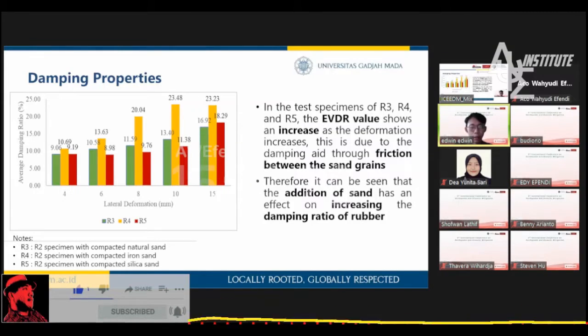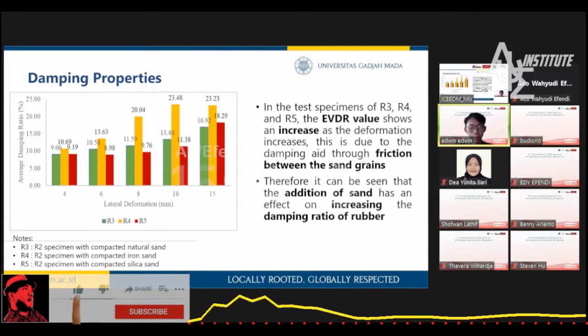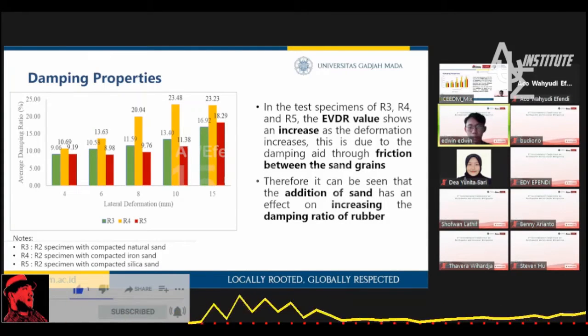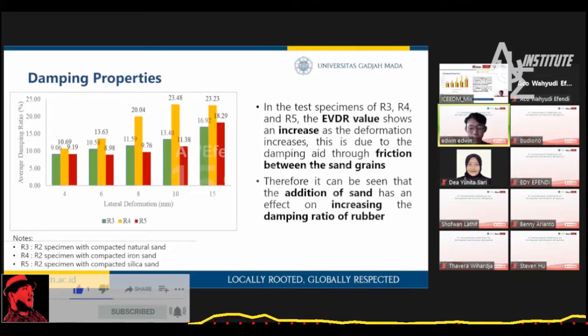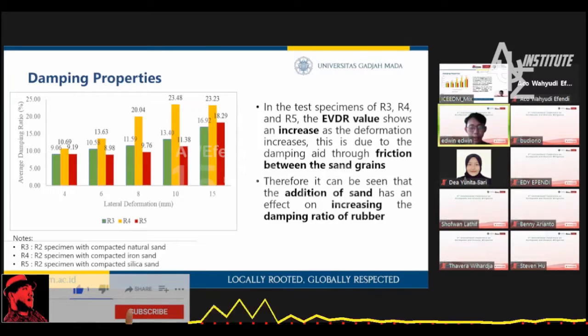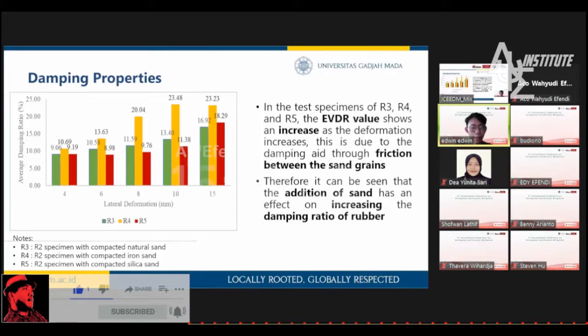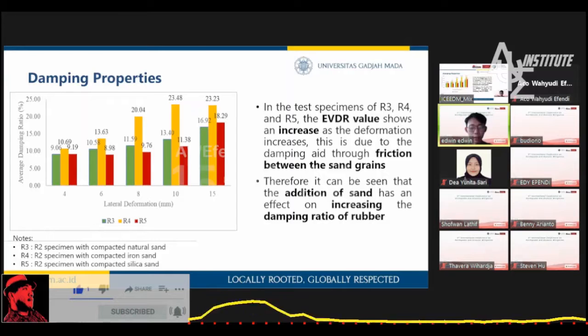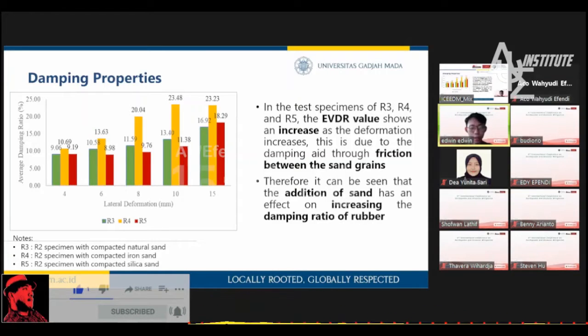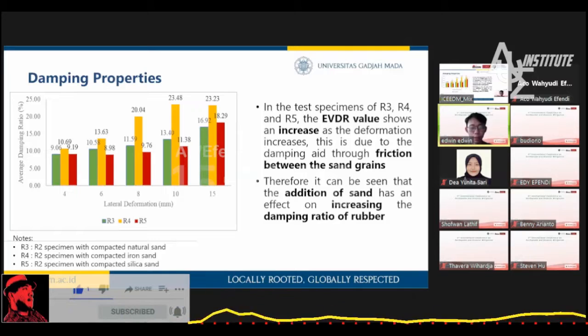The results show that the equivalent viscous damping ratio value increase as the deformation increase. This is due to the damping aid through friction between the sand grains. Therefore, it could be seen that the addition of sand has an effect on increasing the damping ratio of rubber.